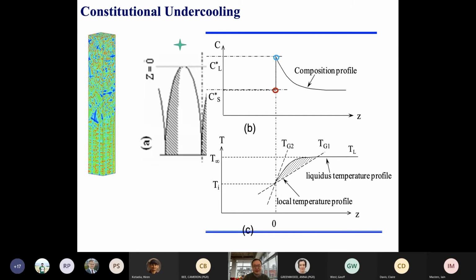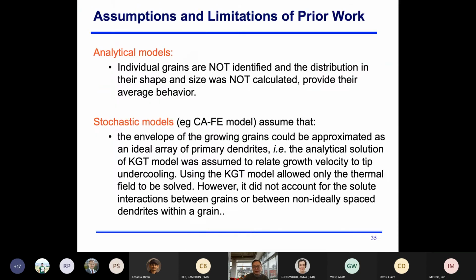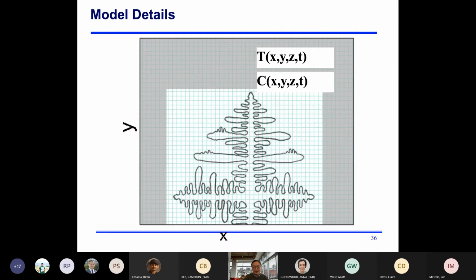So that's the theory, and now we have a computer program to simulate the whole process that I explained to you earlier, right? Now we try to do the calculations. We use a stochastic modeling method, which can use phase field, and we use the CAFE method to do it. Essentially, we solve the temperature against time and spatial location with concentration profile, and those two are globally solved. And then you will also solve the solidification front, essentially to determine the solidification rate, and then move the interface around. So that's essentially what it's about.